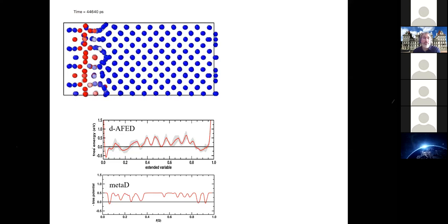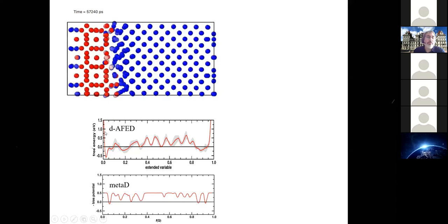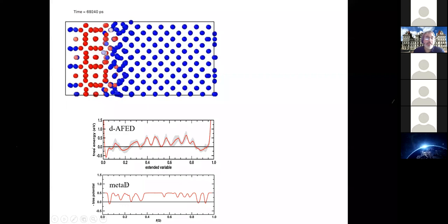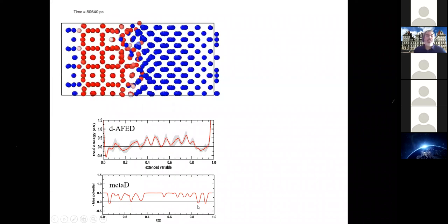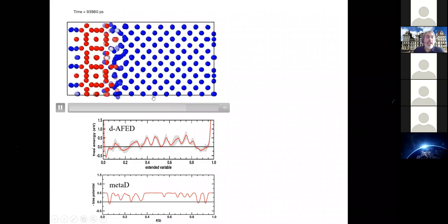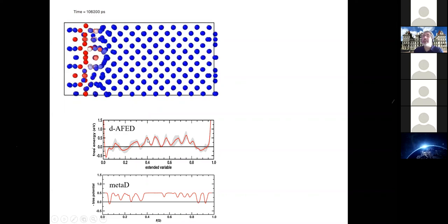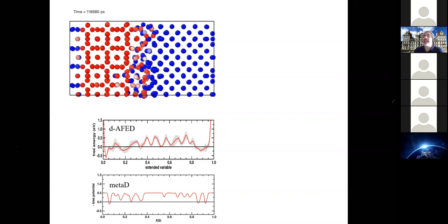And so we ran both adiabatic free energy dynamics and metadynamics on this just to make sure they were giving the same answer. And you can see a bunch of hills that you get from both of them. All right, and those hills are giving you an actual estimate of the barrier for each layer to undergo a transition. And the height of the barrier is about 0.5 eV. So not only are you getting the structural information, you're also getting kinetic information out of this.